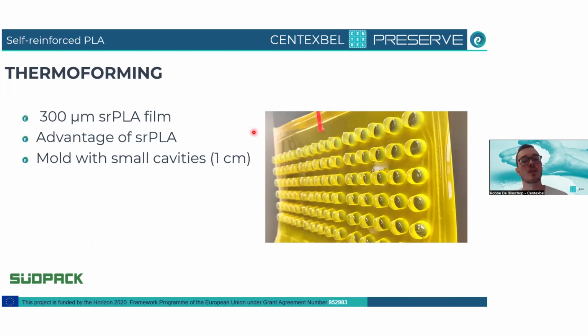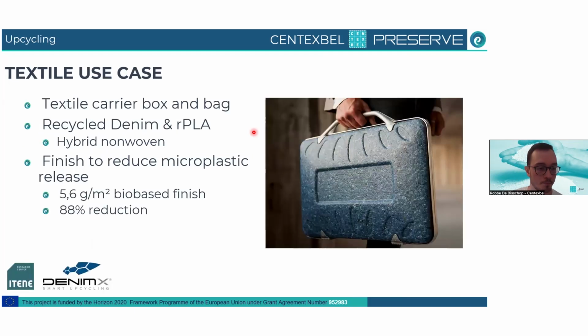When you try to heat it up and then try to create these cavities, try to thermoform, it will break, especially during the edges of the material. But using the self-reinforced PLA film, you can actually very easily thermoform this while also having a very high strength, comparable or more towards the semi-crystalline one, because that is the difference. When you use a semi-crystalline PLA grade, you will have a higher strength of the material.